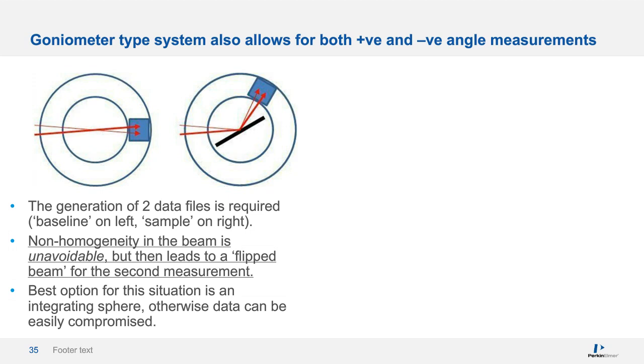In addition, there is another problem. Since the beam is not homogeneous, when we attempt to measure the sample relative to some background measurement, shown here on the left, the beam has been flipped, as it must, by virtue of performing the reflectance measurement itself. So this is simply unavoidable. The problem is compounded by the fact that the detector is also itself non-homogeneous, and different detector technologies will respond differently in this situation. The best approach is to employ an integrating sphere as a means of scrambling the reflected beam to remove detector bias, shown here.